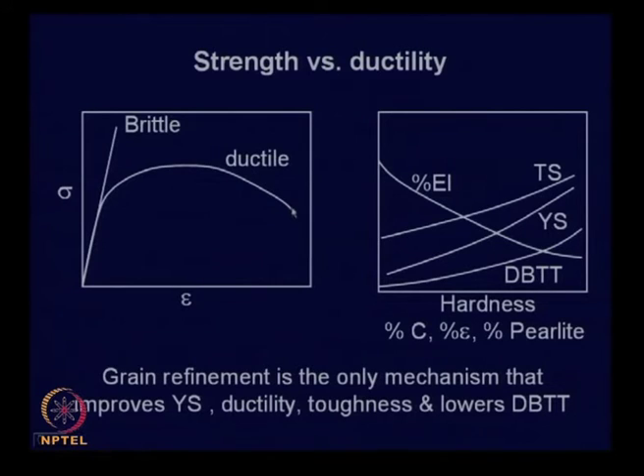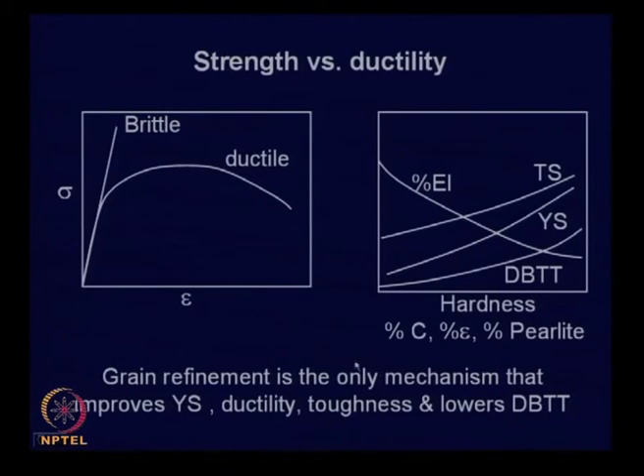So, before it fails, it passes through a necking region, and you have a very large percentage elongation and reduction in area. In fact, it has been seen that if you try to improve the strength of the material, whether by cold working, for example, if you take a wire and bend it repeatedly, each time you bend, you are causing some deformation in the material, and its strength increases, and in the process it reaches its limiting strength, and later you find it breaks. You try to deform it, it breaks. So, that means if you increase the hardness or strength of the material, its yield strength or tensile strength, then its elongation, its ductility, decreases.